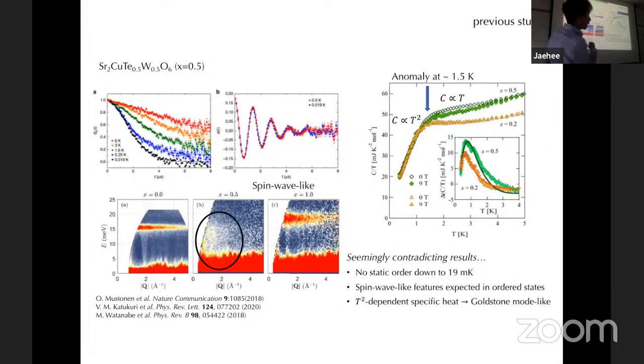Now, when x equals 0.5, the 50-50 mixing case, in muon spin relaxation they didn't find any signature of long-range order down to 19 millikelvin. And in the Nature Communications paper, they claim, oh, this is a quantum spin liquid. But now, in this PRB by Watanabe et al., they measured the heat capacity, and they have this anomaly around 1.5 Kelvin, between 1 and 2 Kelvin, below which the specific heat behaves quadratically. Similar to Goldstone mode as well.